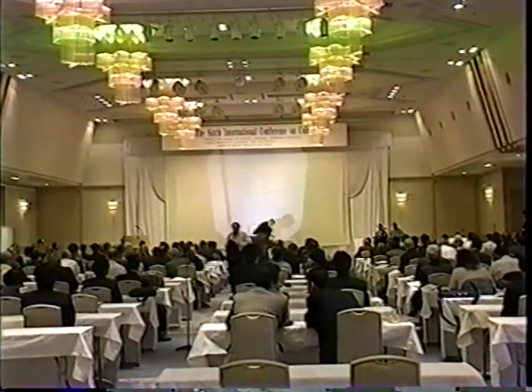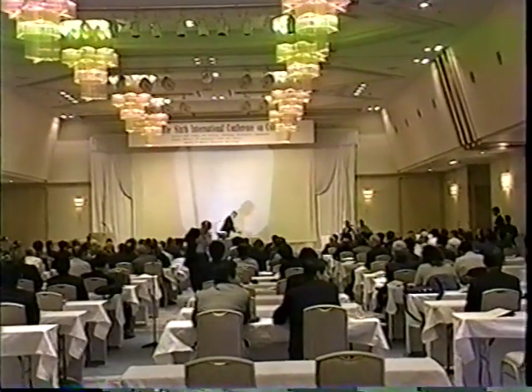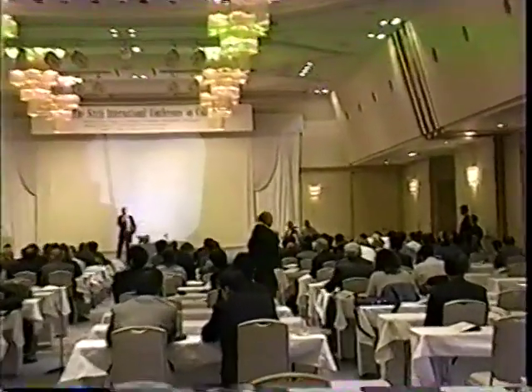Okay, Mike, in your first slide, you show that in your experiment, there is a constant endothermic region. So HFE is always negative. So it is very strange to observe positive. Why always negative? Where is this energy going? Yeah, there is no endothermic region. The only endothermic region is the one that I pointed out and Douglas noticed. I mean, as I've said many times, whenever we see a departure from thermal balance, it's in a positive direction. We never see it in a negative direction. And I just showed you an example where that's not quite true, but it's very rare.